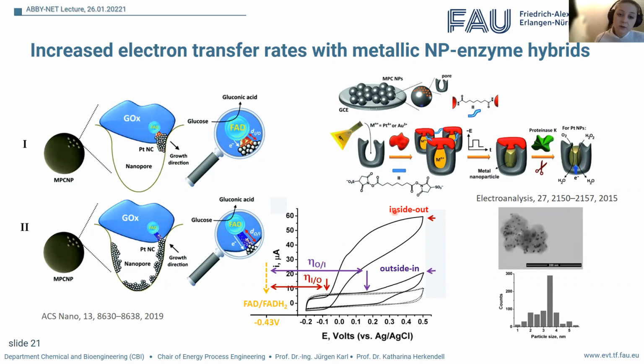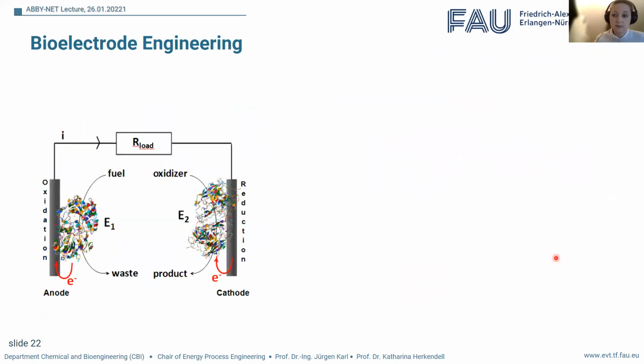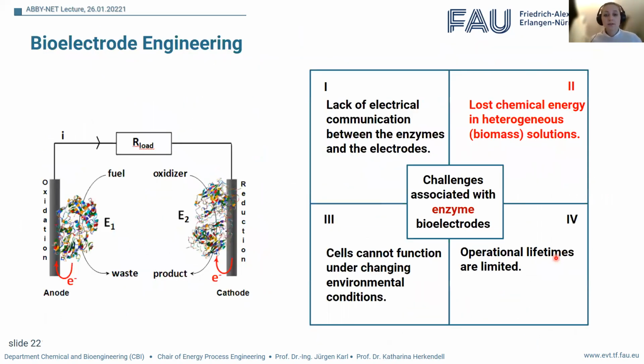And by this, we could actually see for these systems unmatched performance in terms of electricity outputs. And you can actually see that these really grew directly inside the pores and yielded these hybrid systems in this TEM image, where you can actually see a very narrow pore size distribution. Now, let's get to the second problem that we talked about. And I see that we are already quite forward with the time, so I'll hurry up a bit.